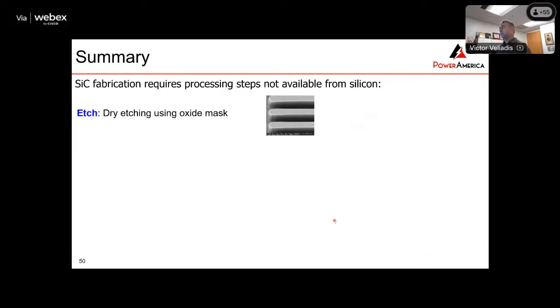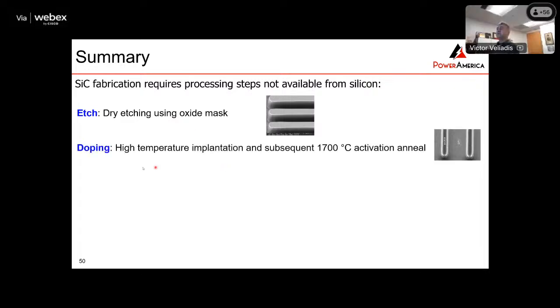Okay, so to summarize my talk, I talked about the steps that you need to take to fabricate silicon carbide in a silicon fab, and basically the process that you need to develop that are specialized and specific to silicon carbide. So they don't exist in silicon. And we talked about the etch, where you have to do dry etching, typically using an oxide mask. We talked about the implantation, the doping, which is basically done with high temperature implantation and then an anneal step at 1700 degrees or above with a cap layer to protect the surface.